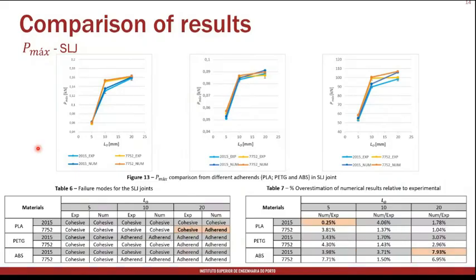Here we can see that we have a good coherence between failure modes. We have only one of the conditions that do not match. We have a significant increase of the maximum load, 5 and 10 millimeters of overlap, and we have a stabilization up to 20 millimeters, which is mostly linked to the fact that the failure starts to occur in the adherend. In terms of maximum effort, it was 8% for one specific condition.